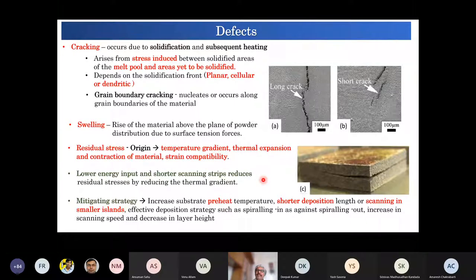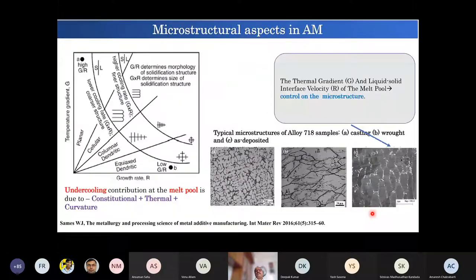Then there is another way to reduce the residual stresses: one can increase the preheat temperature so that the thermal gradients are minimum, or use shorter deposition lengths so that not so much heat transfer occurs there. In that case, it's almost optimized. And then these things can be taken care of, but again, that affects the kinetics of the process and therefore the economics of the process.